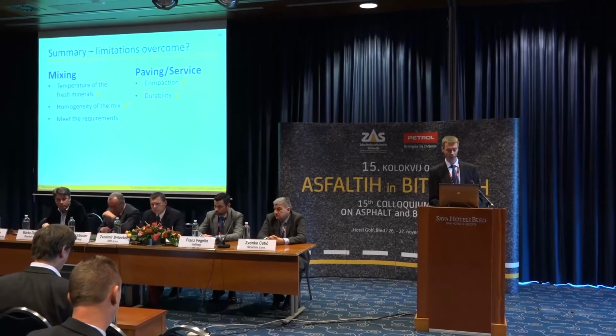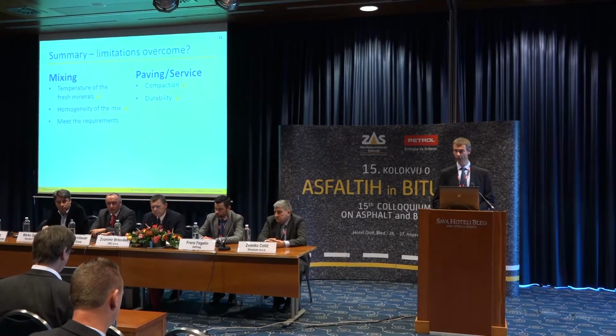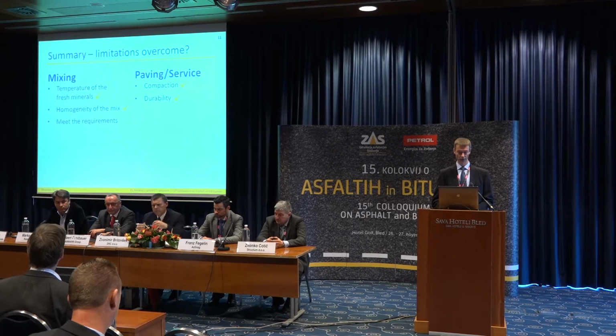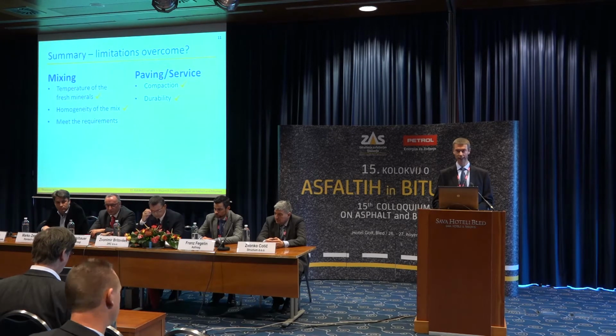The additive can also help to meet the requirements for the asphalt. However, if the binder in the RAP was very strongly aged, it's very hard and brittle, then additional measures have to be taken. For example, as we heard from the Austrian colleague, the usage of a softer fresh bitumen or the addition of a rejuvenator.